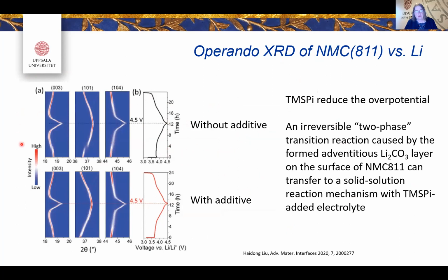Without the additive, you have a problematic two-phase reaction taking place, with the lithium carbonate layer often found on the surface of this NMC electrode, which can be crystalline. But with the additive, you seem to have a solid solution reaction between the additive and this carbonate, which actually is very positive for the function of the battery.